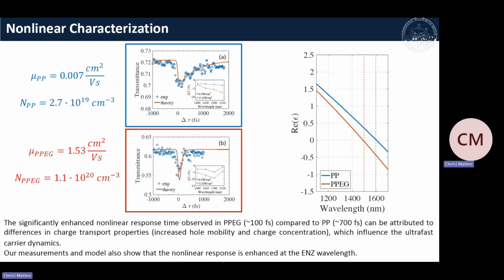So we went back in the lab and measured the mobility and the carrier concentration. And we found that, yes, the mobility dramatically increases, but also the carrier concentration is different between the pristine PEDOT:PSS and ethylene glycol doped PEDOT:PSS. So we attributed the change in time, which is like 7 times shorter, between the pristine and the doped PEDOT to this change in the mobility that is due to the extra doping.